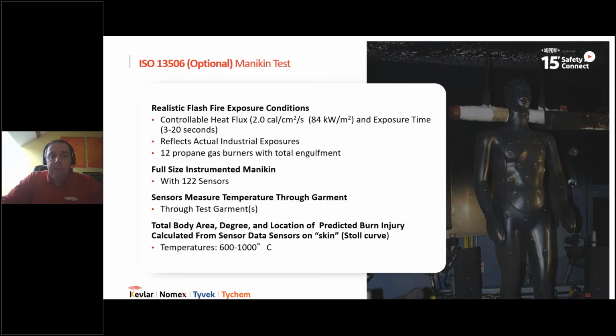And you generate heat and flames with 12 propane burners that will fully engulf the mannequin, generate a heat between 600 and 1000 degrees centigrade inside the chamber. And you're measuring the heat going through the garments with the 122 heat sensors that are a little bit everywhere on the mannequin. Now, with that, you really get concrete data. You will see what is the level of second and third degree burns sustained after such a flash fire exposure. You see where the burns happened. And with the translation according to the Stoll curve, you also see the chances of survival based on the burn rate injury that would have been sustained in such a case.